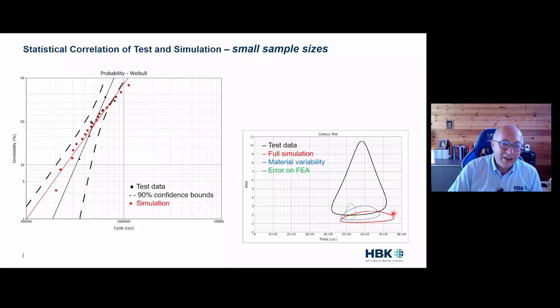But more than that, if we look, we can start to see how material variability and FEA variability compare. Here, the material variability is very broad, yet the finite element variability is very narrow. So what this is telling us is that most of the variability we're looking at is due to material variability. That's an aleatoric uncertainty. We can't do anything about it. Sure, we could invest more in FE, but even if we made this narrower, it wouldn't change our design. So our current approach to FE is good.